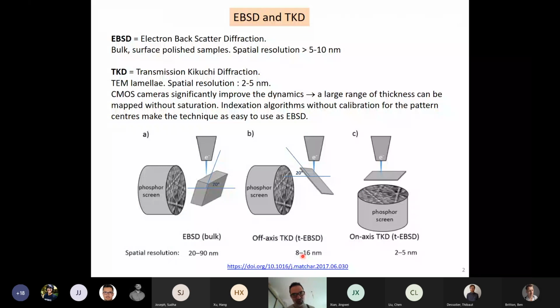So I will try to go quite quickly. I think that all of you know, of course, in your laboratory, what EBSD and TKD are, so I will just go very fast here. In EBSD, you need polished bulk samples, oriented to collect the Kikuchi patterns to get the orientation of each grain or each pixel under the electron beam. And in TKD, transmission Kikuchi diffraction, you use a thin TEM lamella to increase the resolution. Well, it's a slight increase, but I will show you that it can be significant.